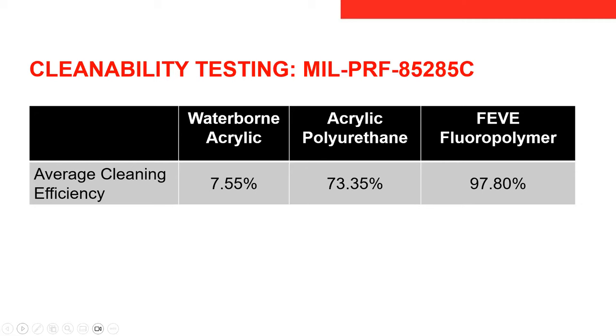And again, even though they're different tests and different situations, you saw something that was similar with the graffiti removal, and that the water-based acrylic, of course, a little bit softer film, wasn't able to withstand that, and especially the cleaning as well. The fluoropolymer was much better, and the polyurethane fell in between. So again, trying to correlate what you could expect in the real world as far as the ability to keep some of these structures clean.